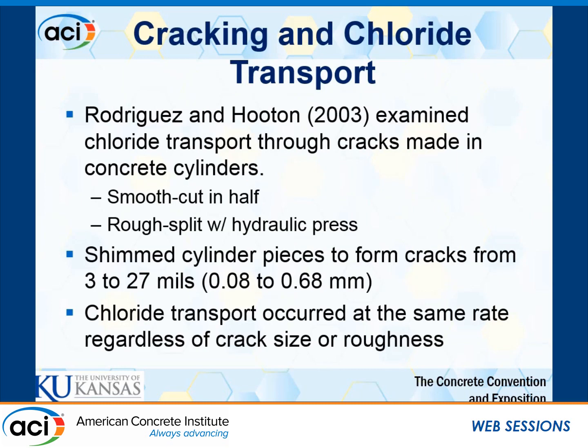So a little bit of background research on that. Rodriguez and Hooton a while ago looked at chloride ingress in cylindrical specimens. They split some of those and varied the crack width between 3 and 27 mils. The main takeaway is that after they measured chloride ingress through those specimens, they saw that regardless of crack width or roughness, they saw similar chloride concentrations.